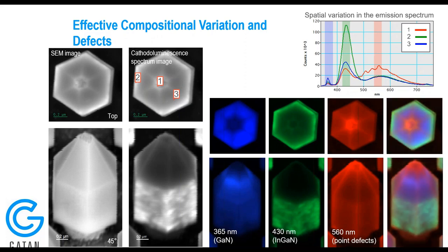By overlaying those three color bands, what we can see is where that relative intensity is coming from. And so you can tell that towards the center of the pillars in the array, you're getting a large influence from the defect band. So with an excitation around the center, you're getting most excitation from the point defects, and towards the outside you're getting mostly the quantum well effect.